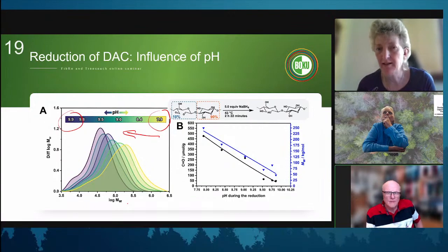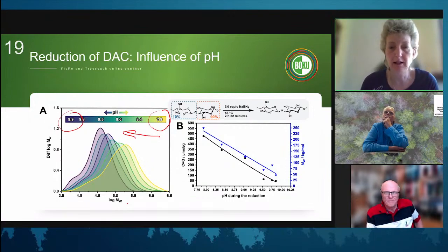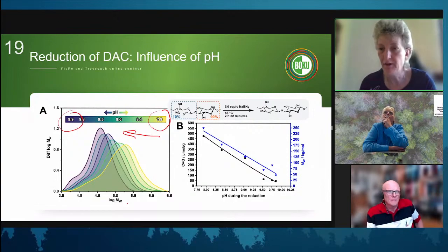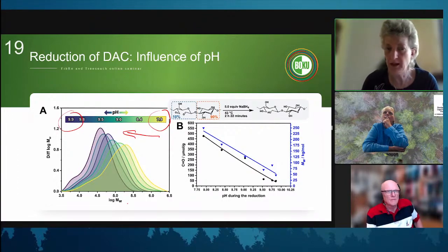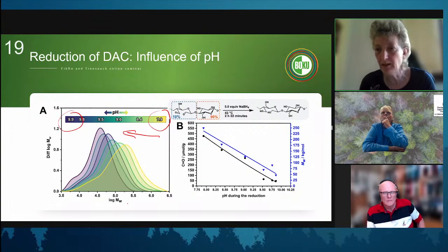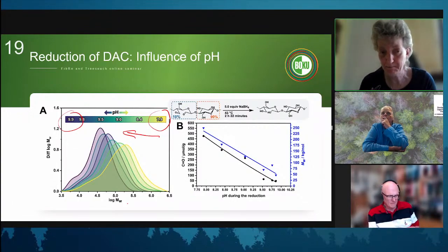Yes. And this has been a great concern for a long time, also in paper conservation. If you have a historic paper with keto groups and you run those papers in a mass deacidification, which is basically pH 8, 9 something, the fear is always that you degrade more by beta elimination than you do good for those papers.